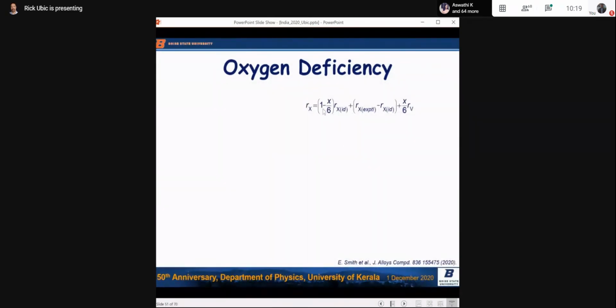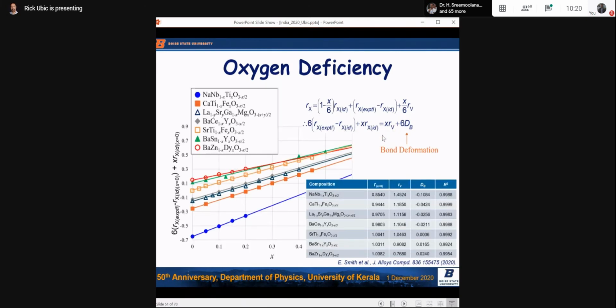And from stoichiometry, we have this. These are the 3 components. So this is the ideal Shannon contribution to the anion size. This is our bond deformation contribution. This is the contribution from anion vacancies. We solve that like this. We just call this y. It's all constants here. This is the equation of a line. Y equals mx plus b. So the bond deformation, which I'm now calling dB, is 1/6 of the intercept, and the vacancy size is the slope of this line. So we graph these lines, and there we go. There's all the lines. There's all the values we found.